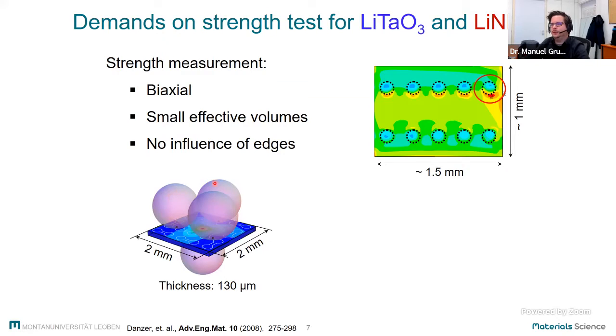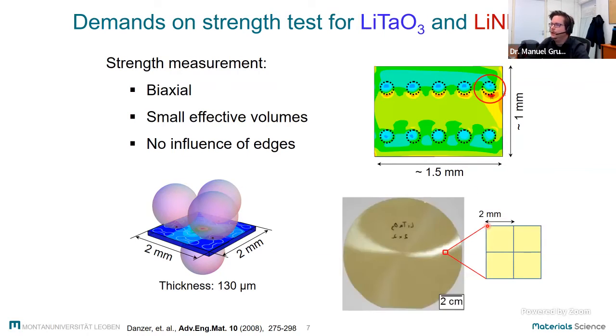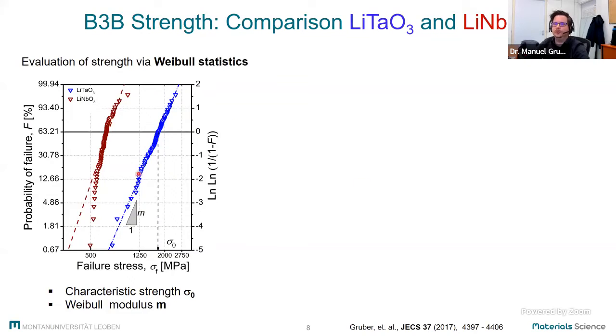Thereby the specimen is supported by three balls on the one side and loaded through a fourth ball on the center of the opposite side, leading to a well-defined biaxial stress field in the center of the specimen at the surface of our sample, so comparable to what we see in a real surface acoustic wave device. So we cut out specimens with these dimensions and did the mechanical tests. And here are the first results.